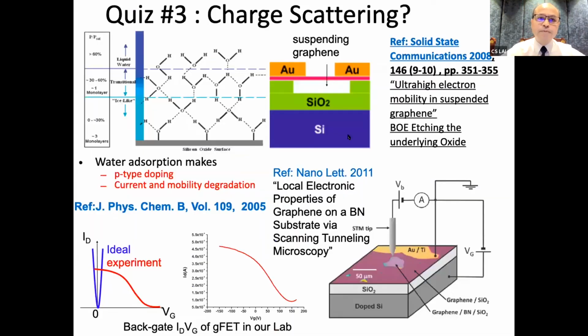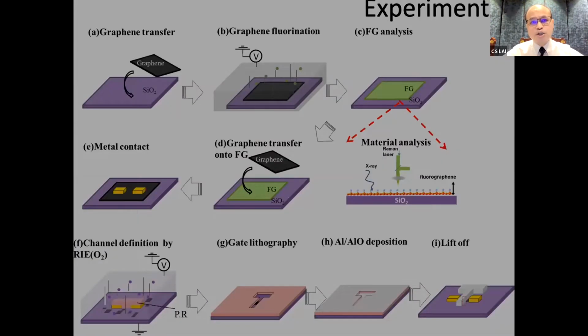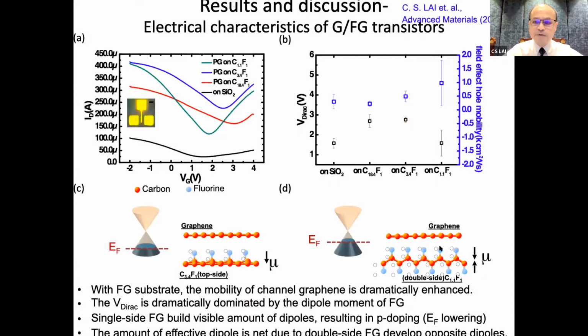After the introduction of fluorographene, I will introduce how to improve mobility by preventing charge scattering. Charge scattering damages the charge transport in 2D materials. One way to prevent charge scattering is by suspending graphene, empty with a void. But our approach is to prepare fluorographene. Here is graphene. We prepare fluorographene underneath the graphene, with partial fluorination or full fluorination. Here is the fluorination for the graphene top side and bottom side.